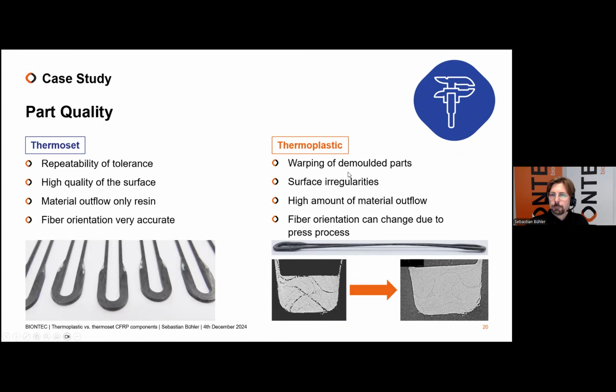For the thermoplastic route, after the demolding, we have a little bit of warping of the part, because this is due to the thickness of the part, because it's very thin. At the beginning, we had some surface irregularities, but later on we gained a very nice surface, as you can see here. And we had to handle a very high amount of material outflow. And later on, a big question is the fiber orientation due to the pressing. What is happening there? Can we still keep the fibers in the perfect direction?